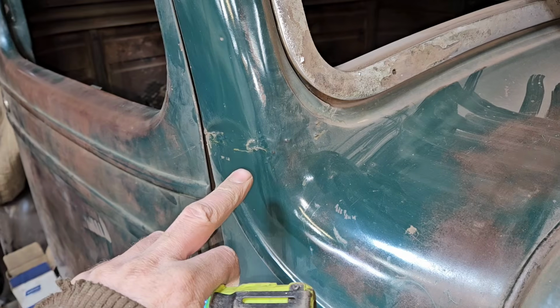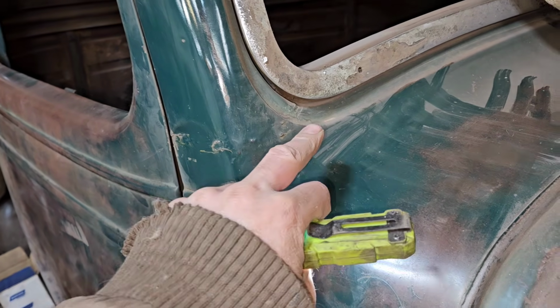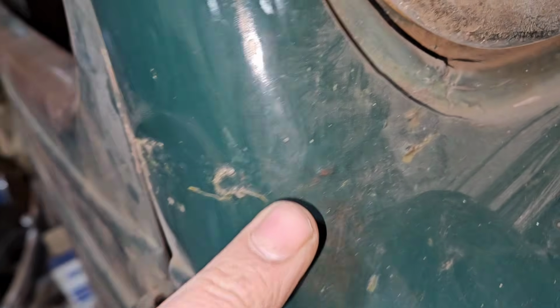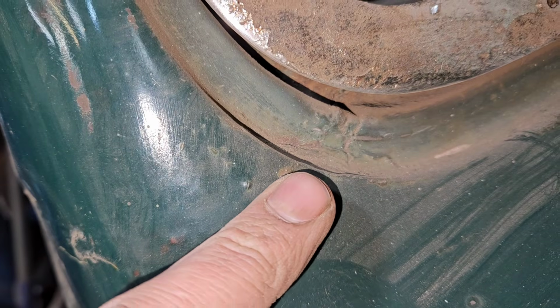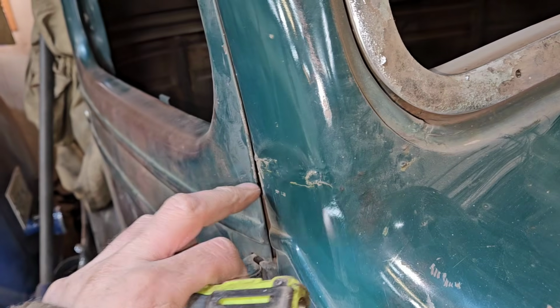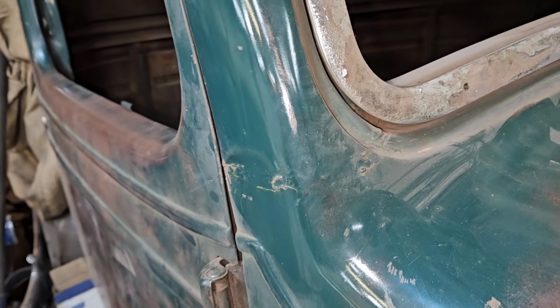Here's a factory lap weld on the A-pillar here. And you can see it hasn't fared as well. The seam was filled with lead, and now it is rusting and causing the lead to crack and lift. This is actually the good side. The other side, the lead is completely fallen out.